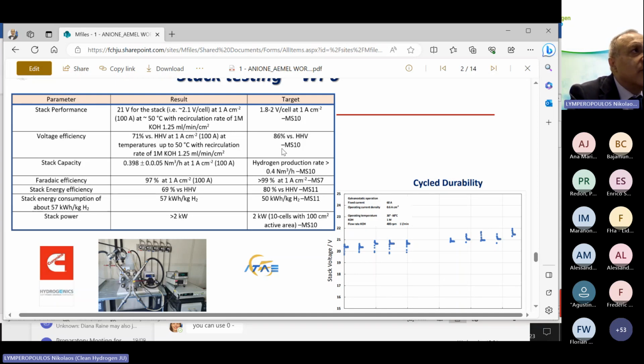And yeah, this was lower than what we have promised, and especially if you look to the voltage efficiency, this is something like 71% versus the high heating value of hydrogen at 100 ampere, compared to something like 86 that we promised in the description of action. And good results for the Faraday efficiency. We were able to achieve the capacity that was indicated in the description of action.